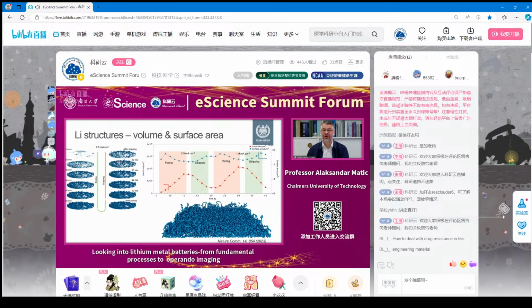If you now follow the volume of deposited lithium, you can see that as expected it increases almost linearly, which you expect for a constant current experiment. But then when you reverse the current, you have the stripping, the volume decreases. But after full stripping, you can see that you still have some lithium left. So this is your formation of that lithium. Doing a second cycle, you again have the increase in volume and then the decrease. But in the second cycle, the deposition on the already formed surface is in this case much more reversible.